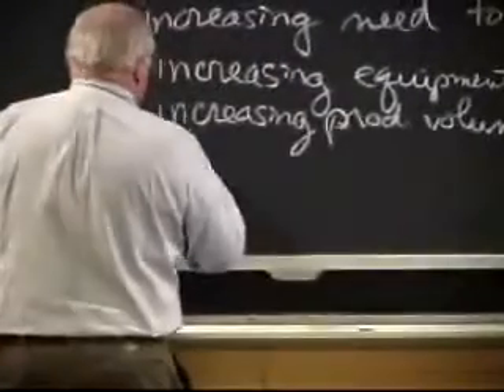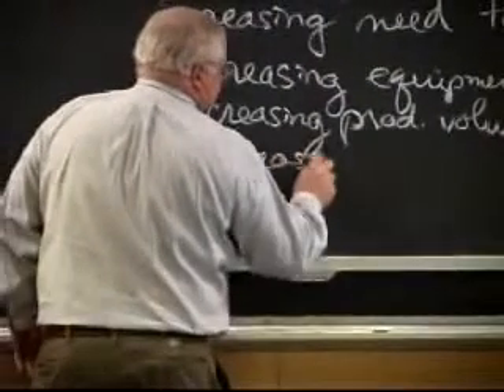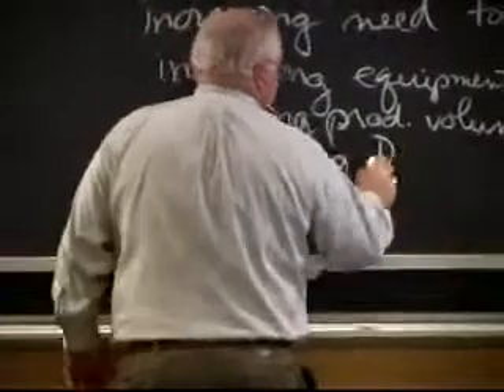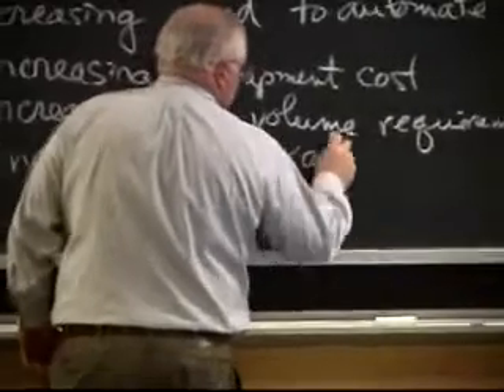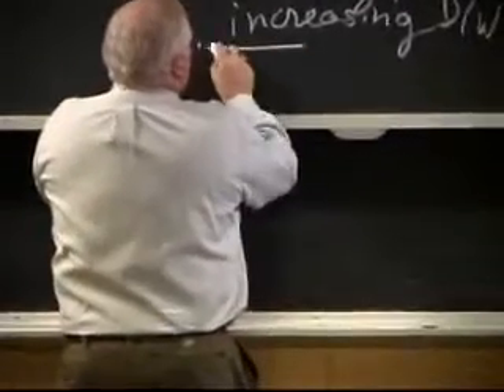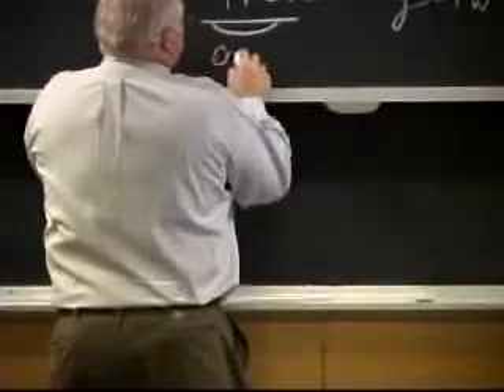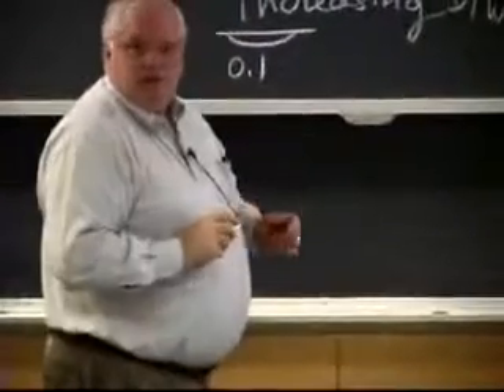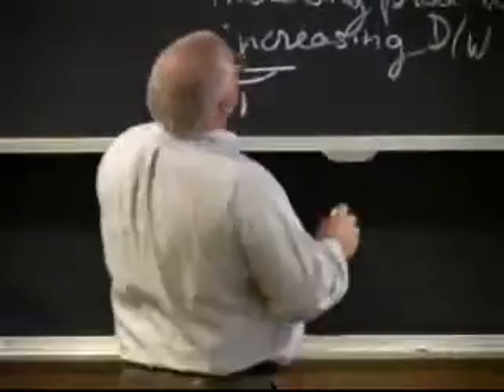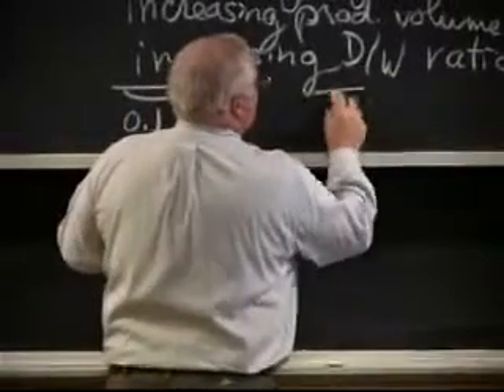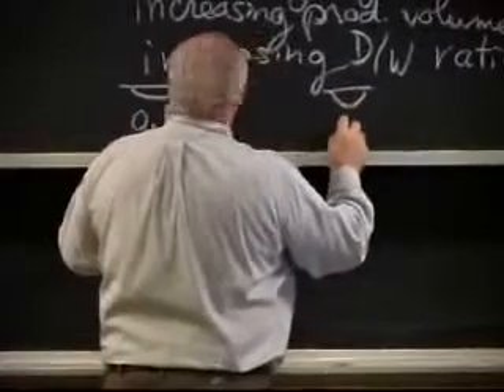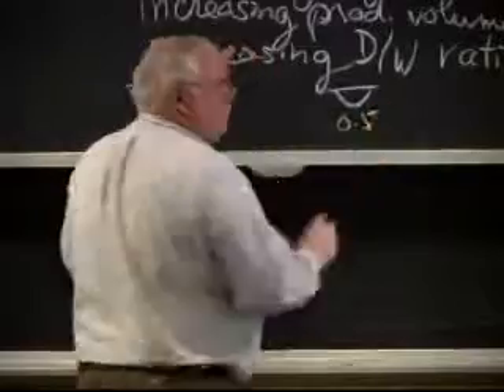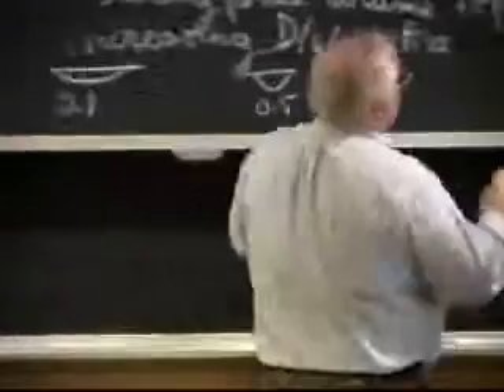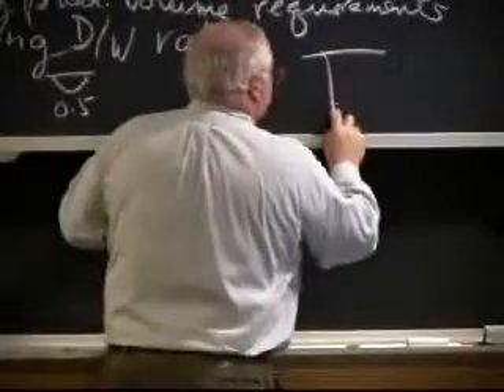which actually adds another thing on this: increasing depth to width ratio. If I go to oxyacetylene, I'll have a weld pool that has a depth to width ratio of a tenth. It'll be 10 times wider than it is deep. If I go to arcs, I'll have a weld pool that will be basically kind of a semicircle. It'll be about a half. If I go over here to laser and electron beam, I can get deep penetration.